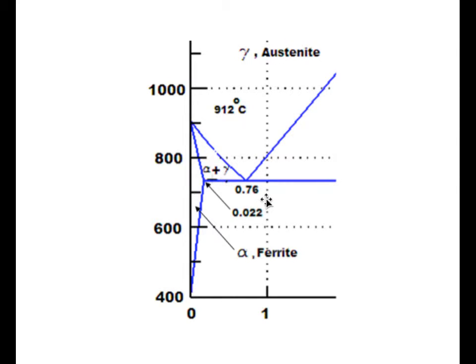So we can choose all alternatives here. Short time at low temperatures, we still keep a lot of the hardness, but start getting the material more useful by giving it some ductility. Or we can increase the temperature and get some intermediate appropriate combination of ductility and hardness. Or we can go for a high temperature a long time and get spheroidite, get a real soft material. It might be rather good for wear purposes with these hard particles within it. It's also good to have if you want to really deform it at cold temperature. So let's look at some pictures of how the hardness changed by temperature and different carbon contents.